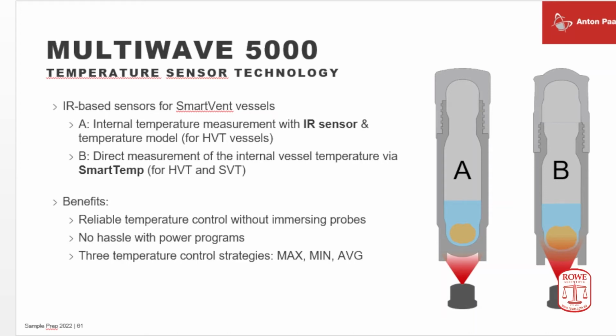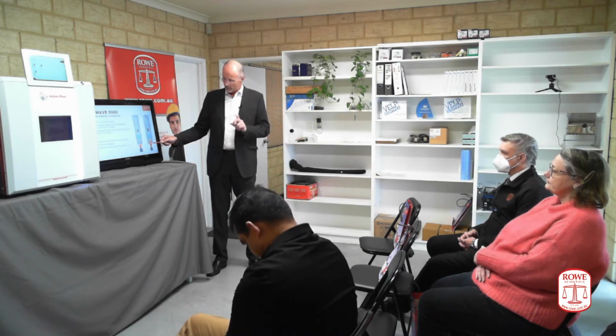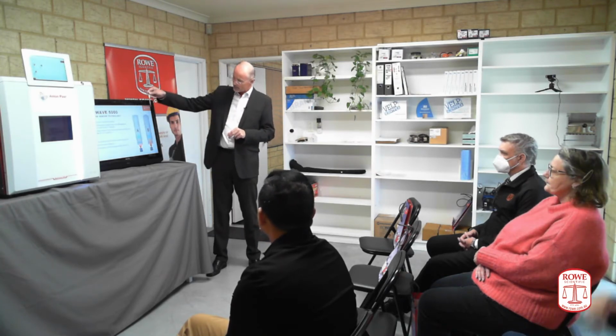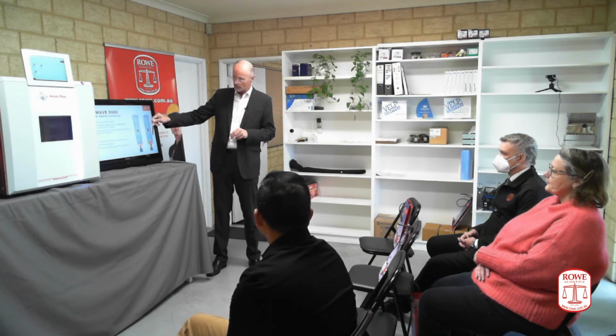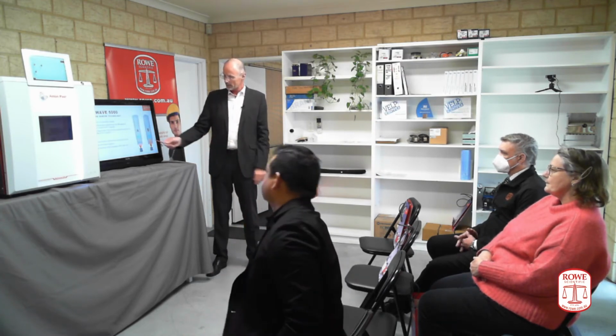And smart temp more or less looks through an infrared transparent window in the PTFE material and directly measures the solution temperature inside. This is a more recent technology described in literature, and it very precisely, directly measures the solution inside without mathematical corrections. What microwave chemists did in the past, they immersed temperature probes through openings at the top into the solution. Immersing probes, I would say, is not state-of-the-art anymore because of tedious handling, the risk of contaminating the sample, and all the cleaning and handling issues involved. So either the classical infrared sensor or the smart temp sensor is the preferred way of reaction control.